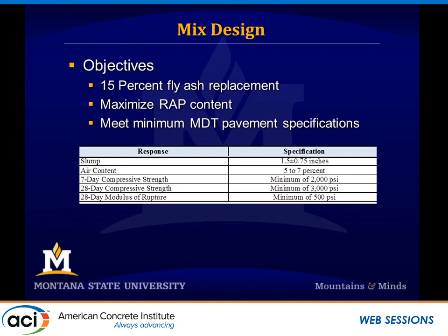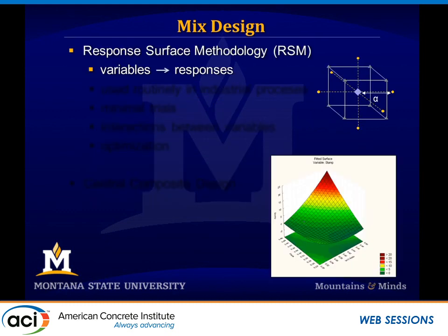So 1.5 inch slump, 5 to 7% air, minimum 7-day strength of 2,000 psi, minimum 28-day strength of 3,000 psi, and rupture strength of 500 psi. So those are our constraints in our mix design. We wanted to meet those things. Okay. Now, how we went about doing that, right?